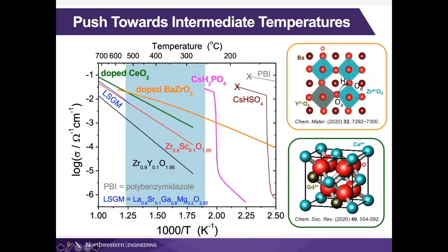and that gives you this very high conductivity. So I'll show you what's been done with this intermediate temperature electrolyte system, because as I said, race to the middle gives us a lot of the benefits of both room temperature operation, which is easy on off cycling, no need to have very high temperature resistant materials, but much better catalysis rates than room temperature operation. And also, as I said, to some extent, better electrochemical efficiency for electrolysis.